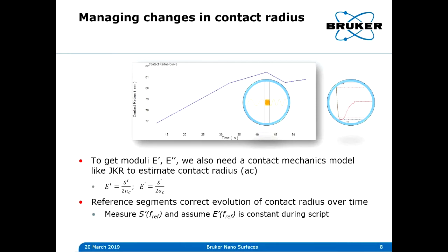Whereas for the AFM-nDMA, part of the utility is the ability to frequency sweep in a rheologically relevant frequency space, which let's call around 1 to 200 hertz. And that enables a very straightforward and facile comparison to a bulk DMA. With contact resonance, you have to start doing time temperature superposition on your bulk DMA in order to get up to the properties at the high frequency that the contact resonance measurement is making. You do have some choice because the cantilever has multiple eigenmodes, so you can sample a few discrete frequencies, but you certainly don't have the ability to sweep, and you definitely don't have the ability to sweep at a rheologically relevant low frequency regime.